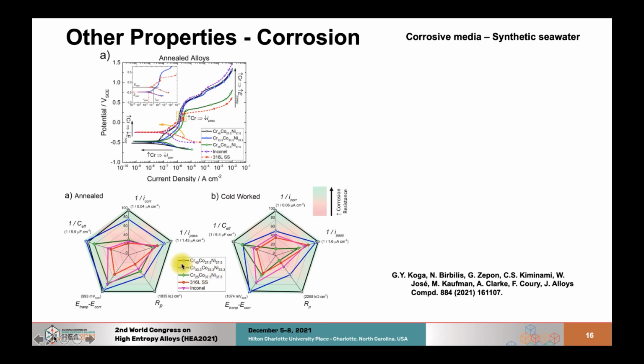And most of these alloys, especially the ones with higher chrome, are better than Inconel 625 and stainless steel. So Inconel is a benchmark alloy for corrosion resistance, and these alloys are much better in terms of corrosion resistance than Inconel. And what's also very interesting is when we cold work, when we put some cold work, 40% rolling deformation, on them, we see that some of these corrosion parameters go up. So this alloy displays a great corrosion resistance in an annealed and cold worked condition, which is very interesting.